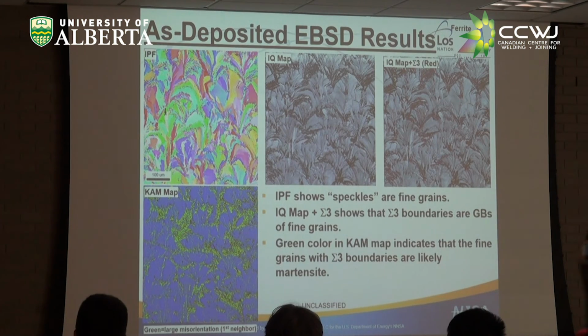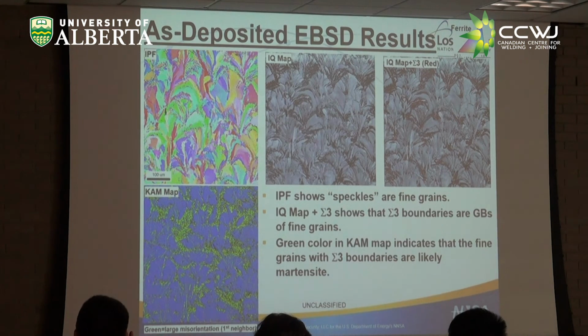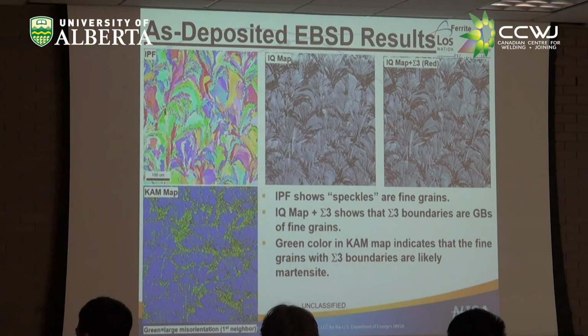So I think, in fact, what we're doing now, we have money from the same office of DOE to do DED additive. I can tell you now because we have the money and we have the equipment to do it. So preheating with high heat and then using real high heat input, if you're familiar with temper bead welding, when you're arc welding, if you can do the same thing, you can end up with the tempered hardness and microstructure. The problem with trying to temper this now is that you can't take that whole reactor and stick it in an oven. So you've got to use the big heating blanket, and it's a big pain to do all that.